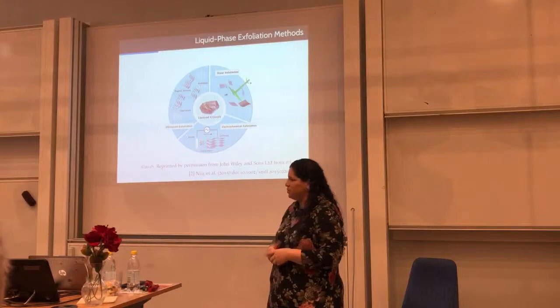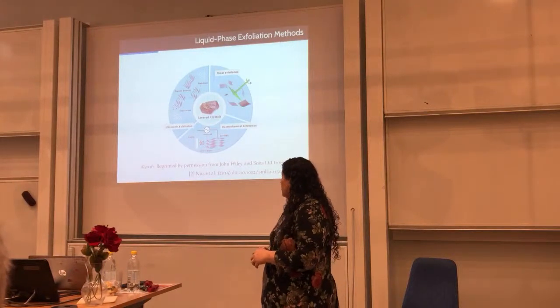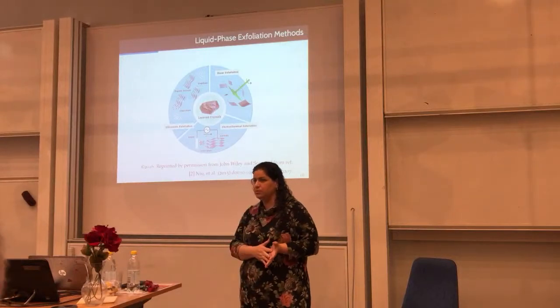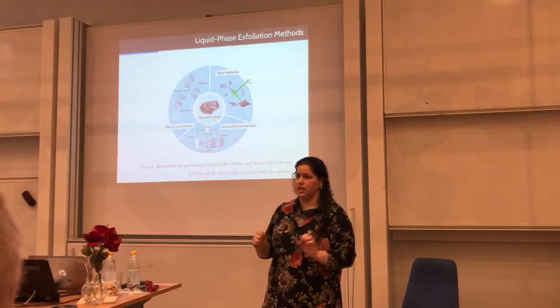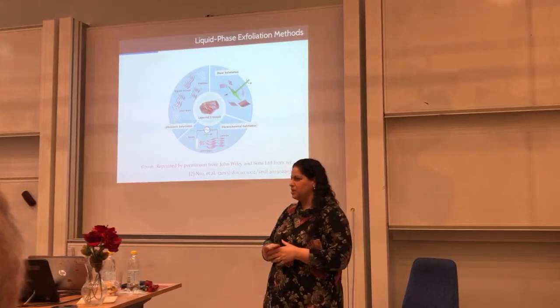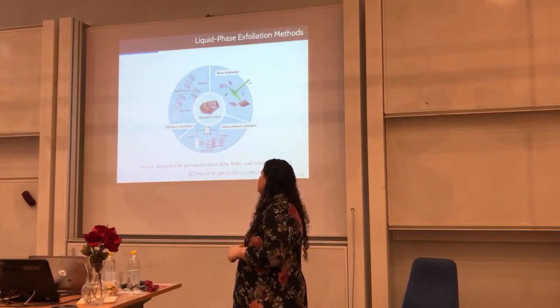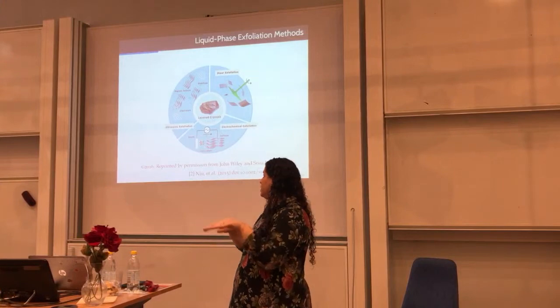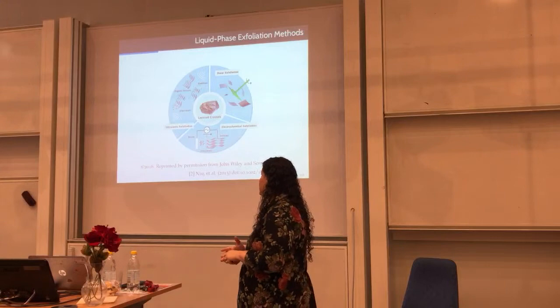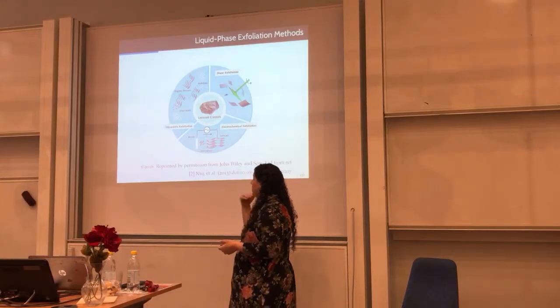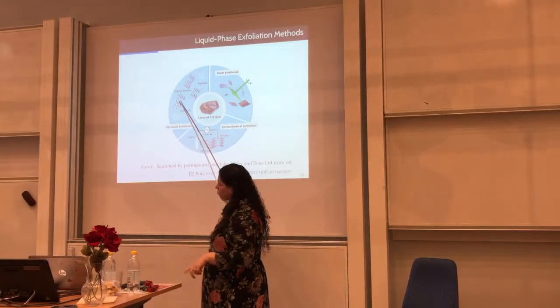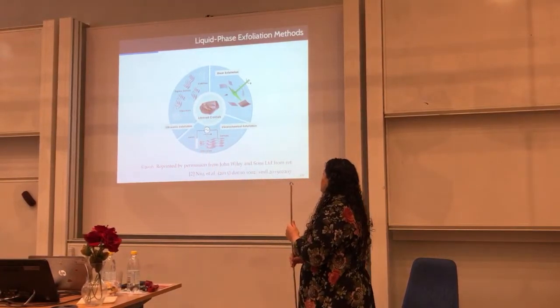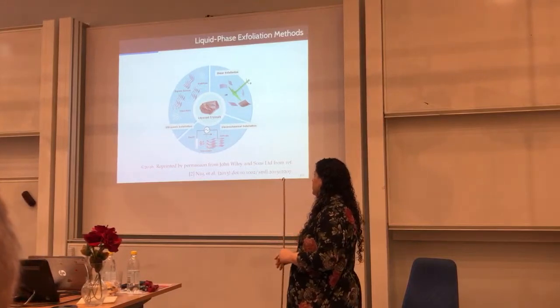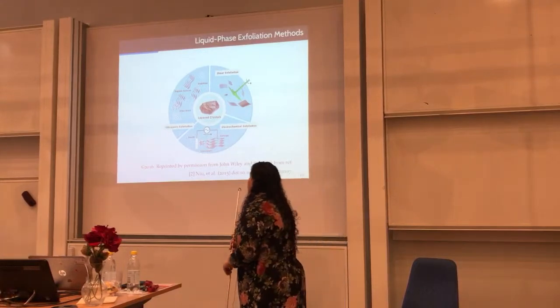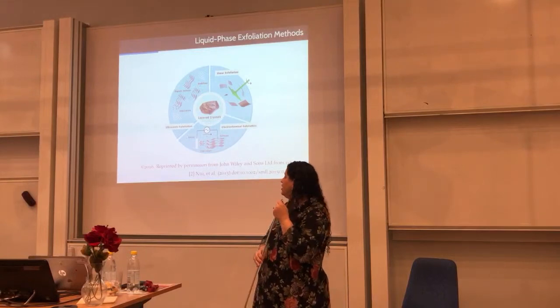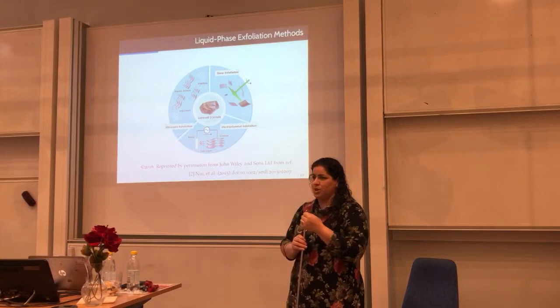Okay. So then how can we do the liquid phase exfoliation? What are the methods that are available to do that? We can use sonication. Sonication is very similar to the ultrasound that you use to make images of babies. The difference is that this is 10 times more powerful, and that's why you can use it to break the van der Waals forces that hold these layers together in stacks, and have them individualized in solution. When you have them in solution, you can have intercalants, like a lithium source, or you can have stabilizers, as we will discuss here, like cellulose stabilizer or surfactants, or you have some great solvents that have matching surface energy, like NMP, N-methyl pyrrolidone, and DMF, that can do the job without anything.